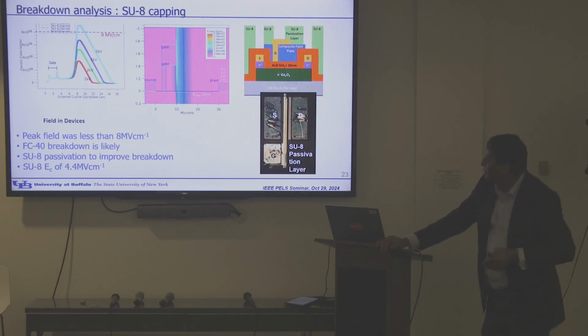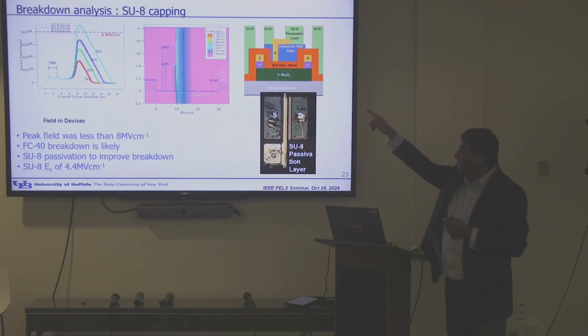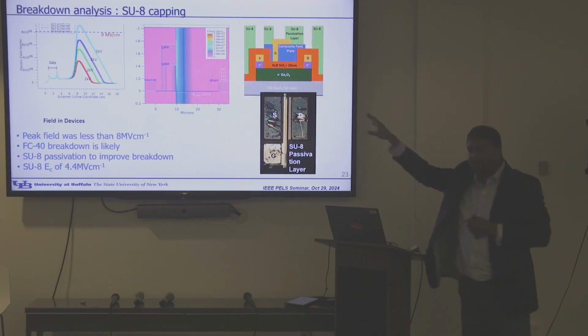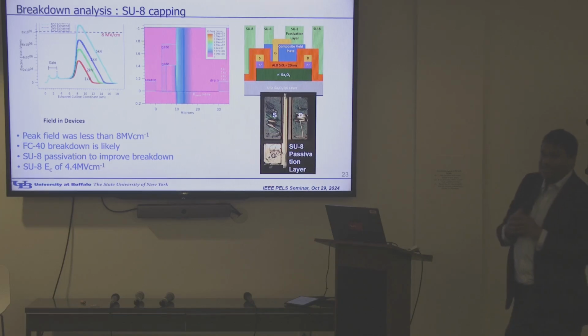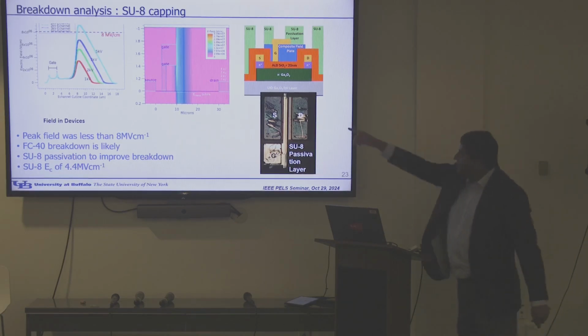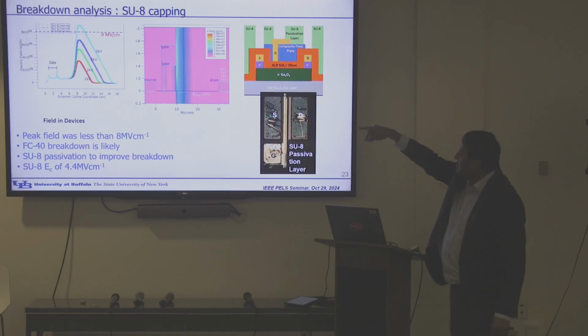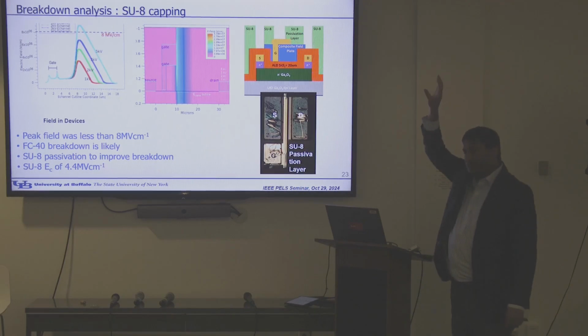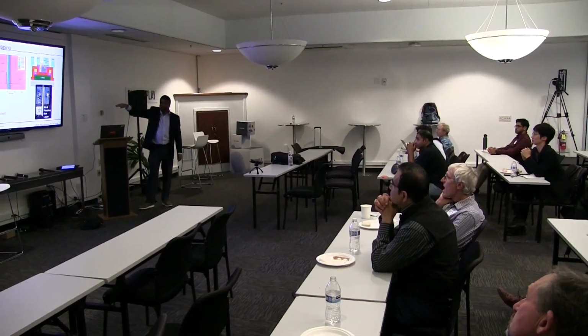And again, the student case, and it's a very good student I had. He was asking, why was it 2 kV? What should be the theoretical breakdown, right? So on the left, you can see he did simulations for the peak field, 1 to 5 kilovolt. Again, if you believe 8 megavolt per centimeter as the highest field, that particular device should have given him 5 kilovolt, but it's giving 2 kilovolt. And he was saying, why is it 2 kilovolt? And what you can see is that in the middle figure here, the blue lines, the high field regions, they actually go outside the gate, right? So they go pretty far out, I guess several microns into the air or Fluorinert. So most likely the Fluorinert is breaking down, not the device. So how do you overcome that?